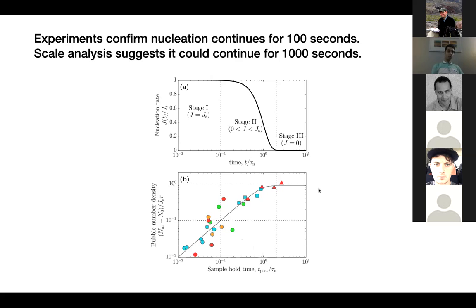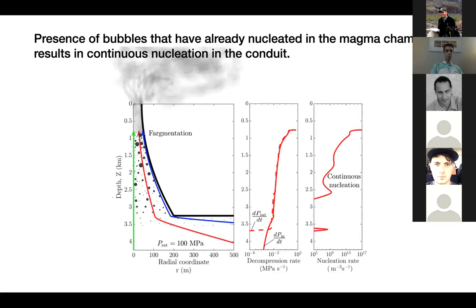The difference between eruptions and these experiments is that in experiments, we stop decompression, and continuous nucleation was basically at constant pressure. But with these Plinian eruptions, with quasi-steady mass discharge rate for several hours, it's hard to imagine that decompression at some point stops for bubbles to nucleate. So we simulated bubble nucleation and growth, this time starting from magma withdrawal from the magma chamber and then throughout magma ascent in the conduit. Water becomes saturated at 100 megapascal, equivalent to a depth of about 4.5 kilometers. We assume that's 1 kilometer below the reservoir roof.